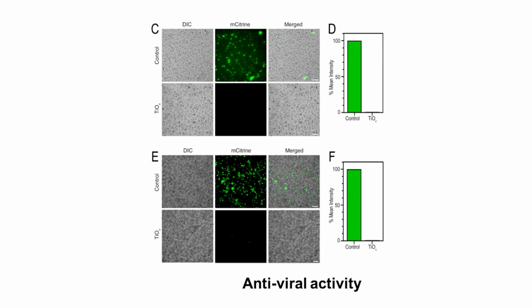Similarly, if we look at the antiviral activity, we tested it against baculovirus, and the green fluorescent proteins basically say, indirectly, the number of viral strains present on the sample surface. You can see a large number of green fluorescent proteins on a glass substrate, and you almost see nothing on the surface coated glass, which says a very high antiviral activity again. We also washed the surface several times, and we hardly saw any change here. So it shows that the coating is very stable.